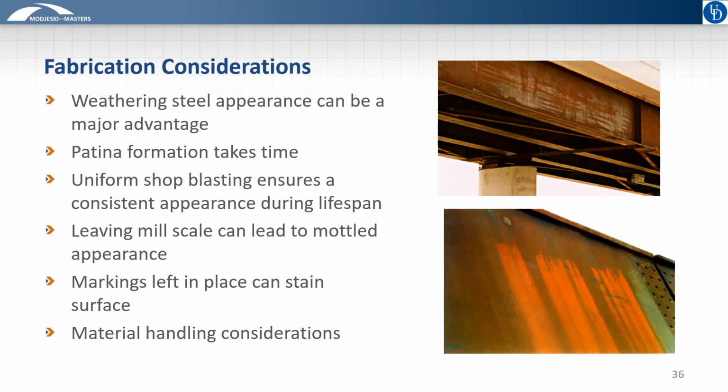The other thing to think about in fabrication is material handling. So how the girders are supported in the shop and in the yard, if they have to remain in the yard for a long period of time. Leaving them on wooden blocking for long periods of time can cause localized areas of discoloration. One of the best recommended practices, if you're going to have your girders in the yard for a while, is to occasionally go out and hose them down and put them through some wet and dry cycles to start the patina formation process early.